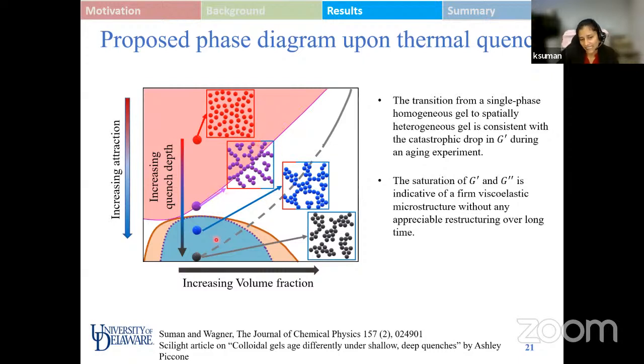With further increase in the quench depth, we enter the two-phase region, and it leads to the formation of colloidal-rich and colloidal-lean phases, which are ultimately interconnected, which leads to the viscoelastic behavior of the material. And with the deepest quench possible, it leads to more and more densification of the colloidal-rich regions, and the interconnection between the colloidal-rich regions gives rise to the elasticity which is observed in this behavior.